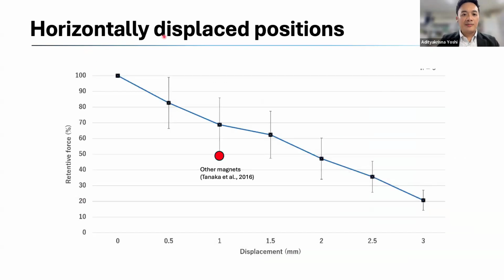Regarding the horizontally displaced position that relates to the automatic reseating feature, a special feature of the magnetic attachment, we also performed evaluation using this new magnetic attachment, and it performs similar or better than the previous magnets, as reported in Tanaka et al. from 2016. So this new magnetic attachment has an improved structure and also has stronger retentive force even in horizontally displaced positions.